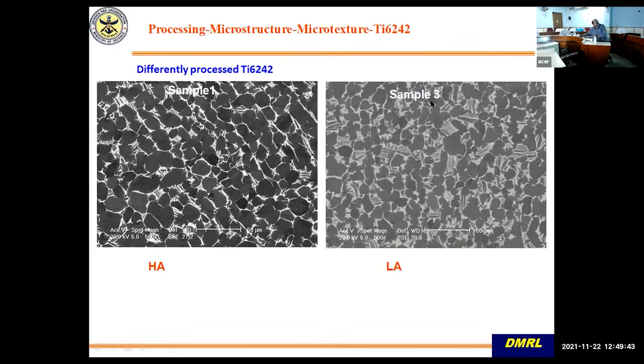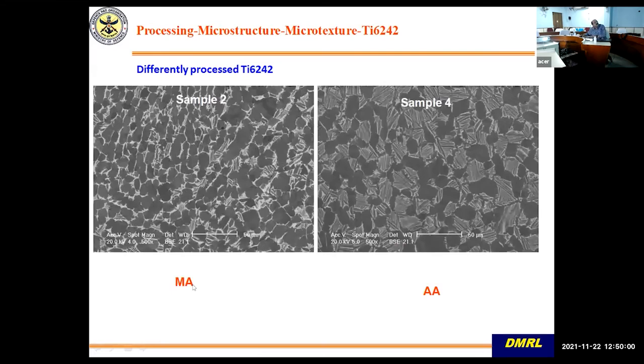So these were the different materials. We took the microstructure, looked at it in SEM, primary alpha, transformed beta. There is a slight difference. These are different materials, sample 1, sample 3. This has got higher attenuation. This has got lower attenuation. This again, another sample, sample 2, sample 4, middle attenuation, and this is anomalous attenuation. So there is a difference in microstructure also. This transformed beta region is more here as compared to this, but there is not a drastic difference.